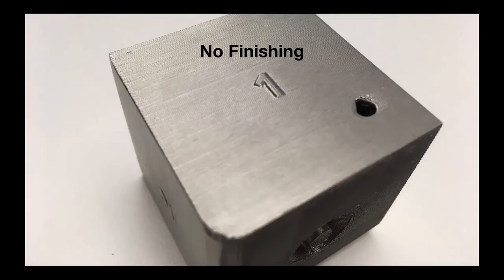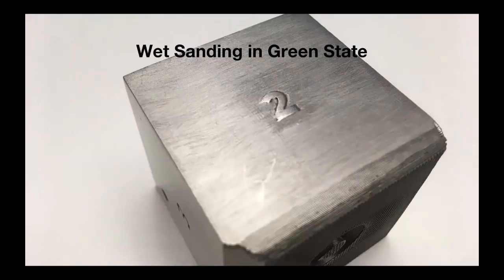When you wet sand it, which is basically in the green state, what you do here is right after printing, you'll take that green part and put it under water and use some wet-dry sandpaper and sort of clean up that surface gently. The advantage here is that because it's in that green state, it's effectively composed of plastic, wax, and metal powder, and it's going to finish much more like a crayon or a bar of soap. And it's very easy to finish, even when you're talking about really hard metals like tool steels. It's not sintered at all at that point, so you're not running into the hardness limitations that you'll run into when that metal is fully sintered.